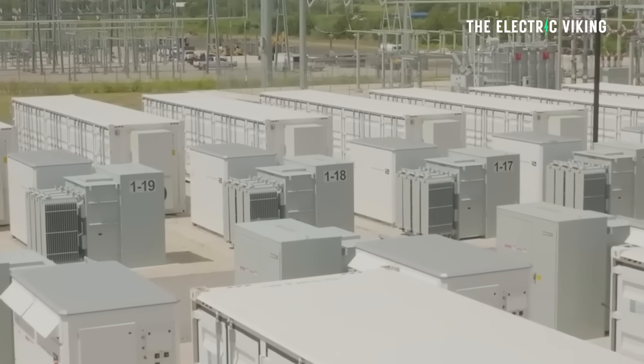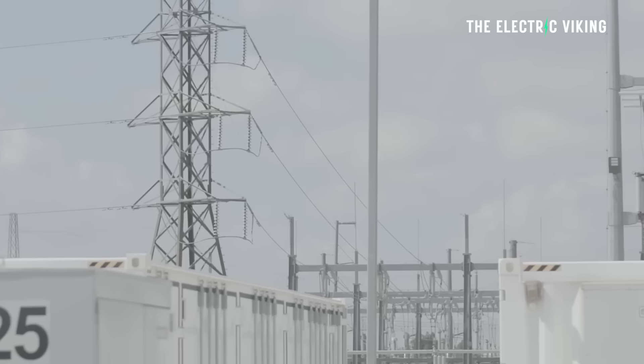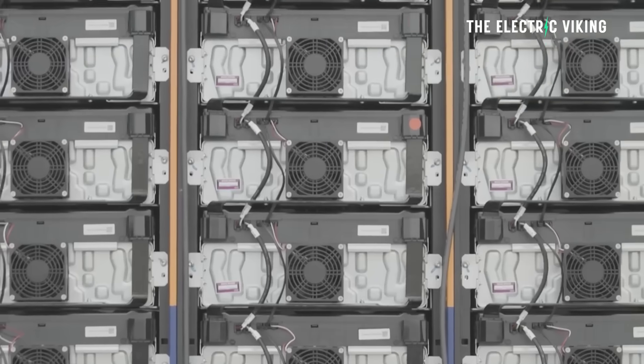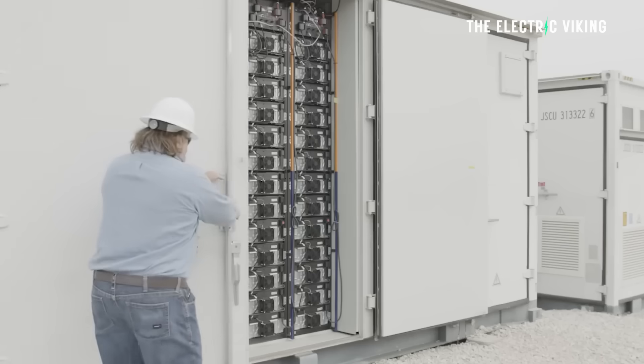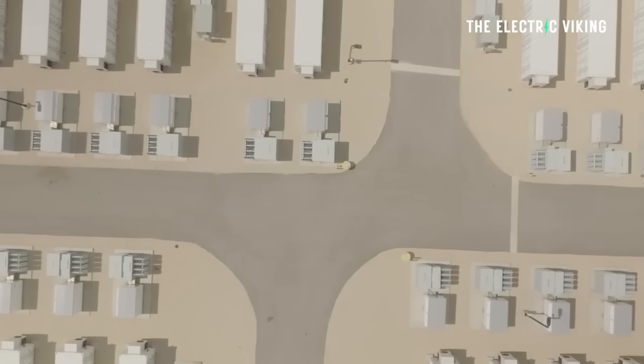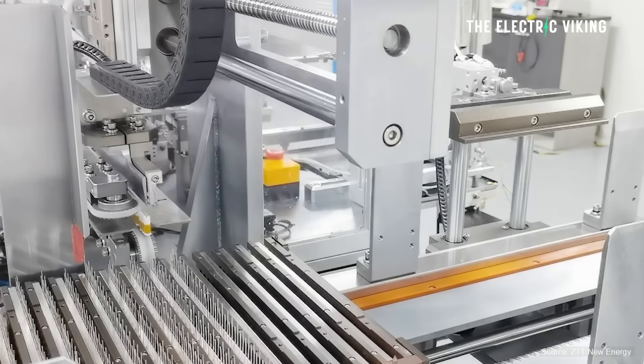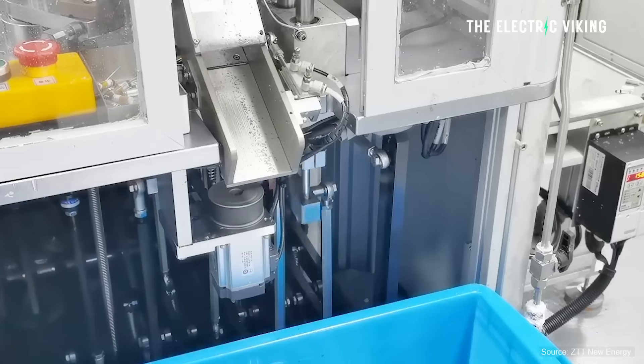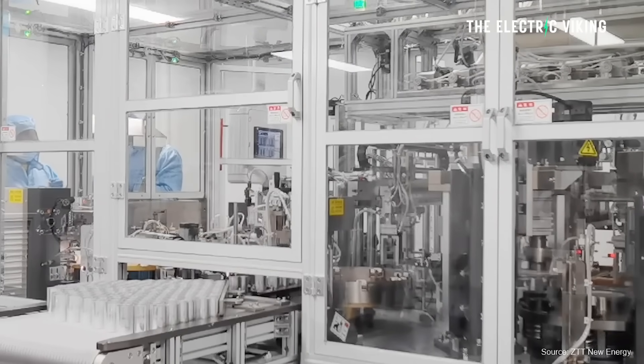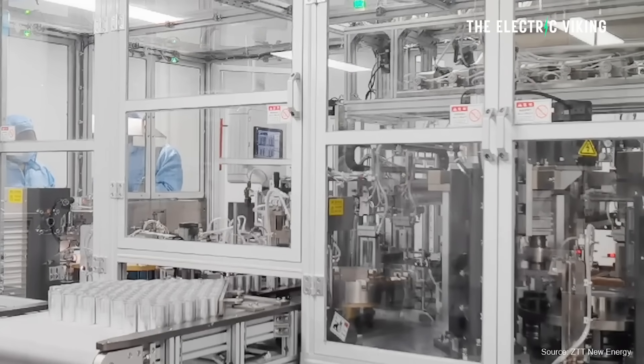This translates to a storage charge capacity of more than 4,600 millifarads per square centimetre, which is much higher than what the researchers were getting before — essentially a remarkable breakthrough. In addition, the material demonstrated exceptional durability, lasting more than 70,000 charge cycles. We should note that in laboratory testing situations when batteries are charged, people often say it won't last that long in real life.